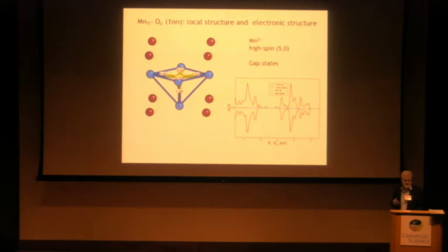The electronic structure, now it's more interesting. The electrons that are donated by the oxygen vacancy go and fill additional manganese up states, and so it's a 5-0 high spin state. There's no occupation of the down spins, and the geometry, I guess, moves a little away from the defect, and the oxygens in the equator move away a little from the manganese. So this agrees with the Cohen and co-worker study in the case of barium titanate.